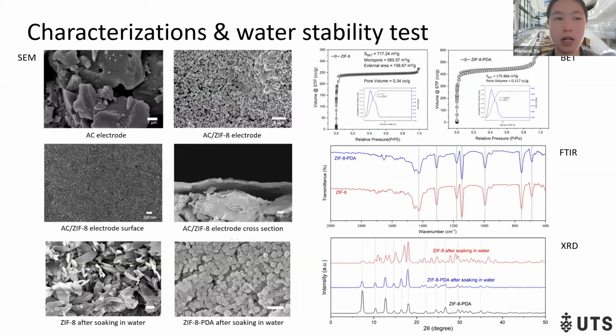Now let's start with the characterization results. From the SEM image, we can see the morphological difference between the bare AC electrode and the modified electrode. The ZIF8 is uniformly grown on the AC electrode surface. After soaking in water, the unmodified ZIF8 shows a structure change, but the ZIF8 polydopamine membrane can still retain its original structure. It confirms that the PDA incorporation improves the water stability.